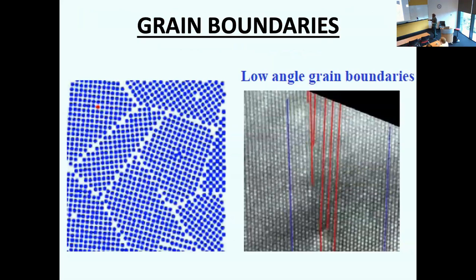So if you don't know, in material science, you have some crystal with some orientation. You can have another crystallite with different orientation, but in fact, real materials are like this. You hardly ever get a single crystal. So these are called grain boundaries. They can be low angle, high angle. The strength, ductility, brittleness, a lot of properties are determined by these. It's a very, very important problem in material science, including your aerospace engine. You have titanium alloys, and depending on what's happening, whether the engine cracks or doesn't crack, whether it's ductile, all kinds of things.